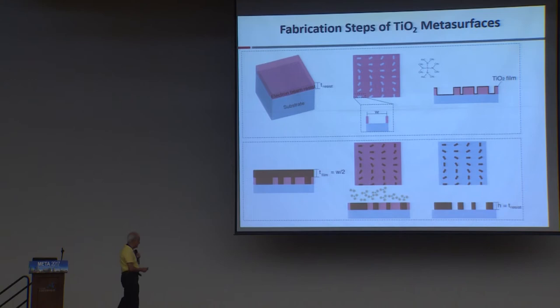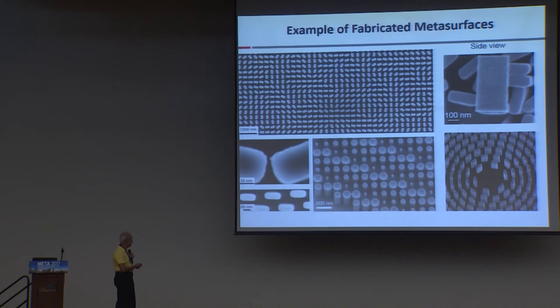But we start with e-beam resist of a certain thickness here. We pattern it. Then we conformally grow - this is a conformal process, atomic layer deposition. It's layer by layer. And eventually, you fill in everything. This is a maximum feature size, let's say. So you fill it up to this thickness here. There is a capping layer. Then you remove the resist, and you're left with a perfect complementary copy of what you started with. Now, the key point, and we have detailed that in a long paper in the proceedings of the National Academy of Sciences, in fact, at the same time as our Science paper, you need to grow to have high-quality and low-roughness in the amorphous state.